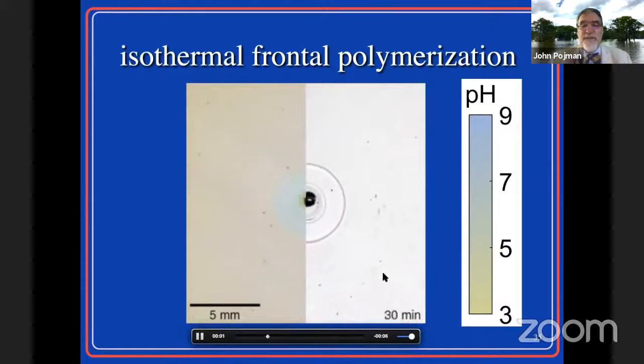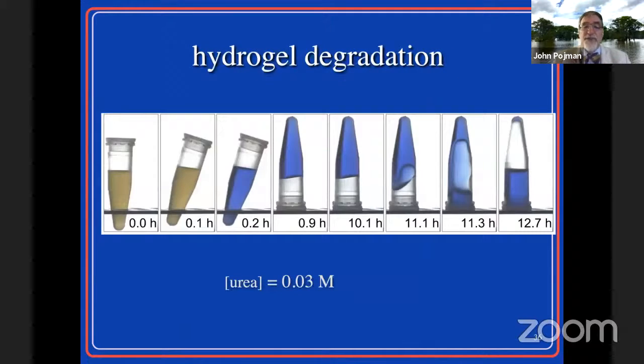To be commercially useful, we have to find a way to make it so that we can store it this way. We want to have a very long shelf life. This system, once you mix it up, after a few hours, it's going to react anyway. So having a front is not such a clear advantage. But it's also possible, by changing the final pH, to get hydrogel degradation. So you get a system that turns into a gel, and then over hours, it will degrade.